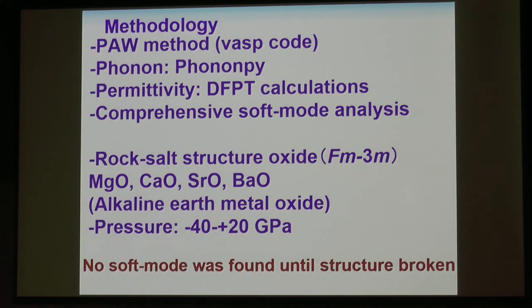The methodology, as shown here: we are using the PAW method implemented in the VASP code, and the phonon calculation is done by the Phonopy code. The permittivity is calculated by DFPT. Then if we have a soft mode, we also plan to do comprehensive soft mode analysis to determine the ground state structure. The calculation was done for the alkaline earth metal oxides, namely magnesium, calcium, strontium, and barium oxide.